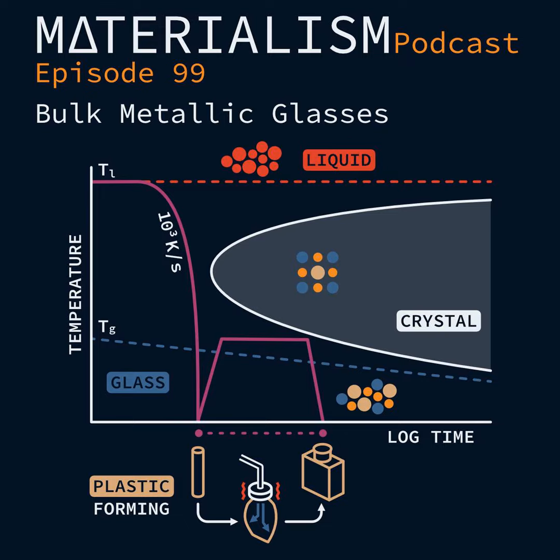I do have one final question, and then we can set up what I think will be a future conversation. The first one is, we just did an episode on high entropy alloys, which people were wild about, and it's been fascinating to dive into that field where a lot of the same things are there. The same things that you're looking for that can cause a frustration of the lattice and therefore a slow kinetic transformation are the same things that give rise to these so-called high entropy alloys, right? And in fact, one of the main reasons why we like high entropy alloys, and one of the things that shock the world, is that they form a single phase with really high solubility limits that nobody sort of expected.